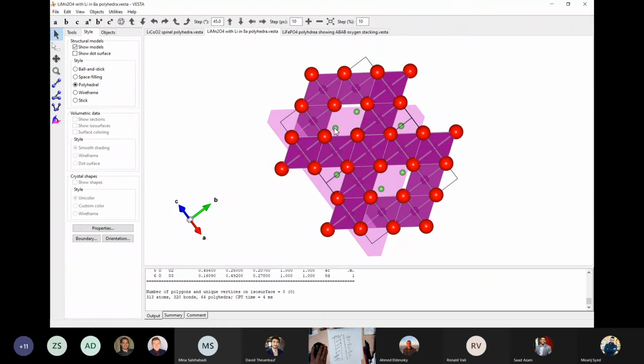And it's very similar to the situation that I talked about before, where there's this change of the site occupancy from octahedral to tetrahedral, just depending on what's more energetically favorable. So when you add more lithium to this system, the lithium leaves tetrahedral sites and goes into the octahedral sites, which are centered in the middle of the tunnel.